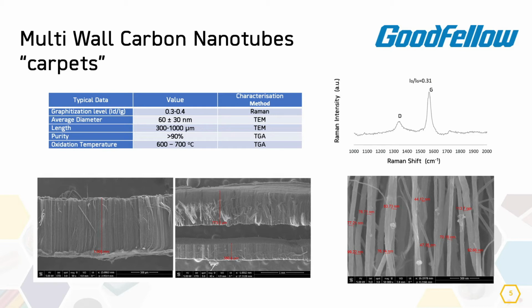What is very important about these carbon nanotubes, which are defined as carpets or forests, is that they are freestanding. Usually, the growth of carbon nanotube forests or carpets occurs upon a catalyst, like a copper or nickel or iron plate. But you can also grow the carbon nanotubes on a quartz substrate. However, these ones are freestanding, which gives the optimal electrical properties of these carbon nanotubes.